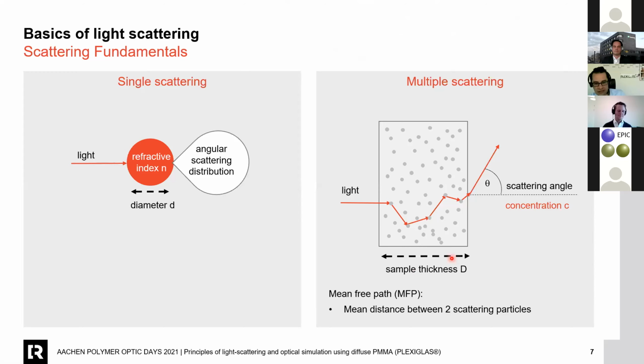So if we look a little bit deeper into the single scattering event, we have a plastic part or an inorganic part, which has a defined size. Here it's a bead, or a defined shape with a diameter. And we have a chemical composition which will determine a refractive index, and this refractive index must be different to the matrix of the matrix polymer. And if a light beam hits the material, we can detect the angular scattering distribution. This is mostly a mathematical function, or can be fitted to a mathematical function. This is the single scattering event.